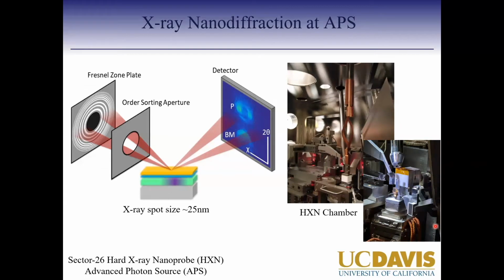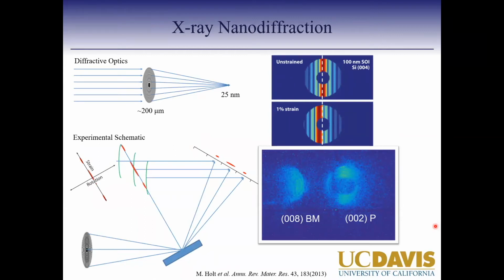Before going into the data we obtained, I wanted to briefly talk a little more about the X-ray nanodiffraction technique. The way it works is you incident the X-ray beam, about 200 micron in size, on the zone plate. That results in diffraction from the zone plate, which focuses down to 25 nanometers. Our zone plate has a center block which blocks the 0th order, and then alternating gold and silicon nitride rings, which cause the diffraction. The beam hits the sample here, and as it moves forward to a detector, let's say placed here, it would again take the shape of this imaging optics.